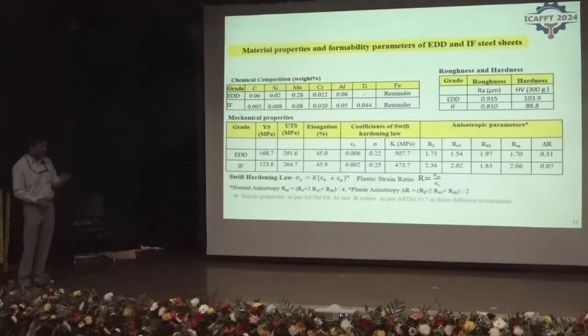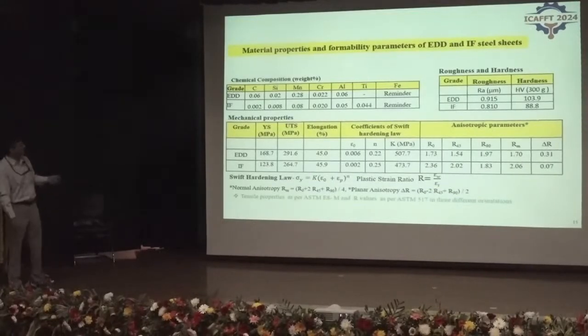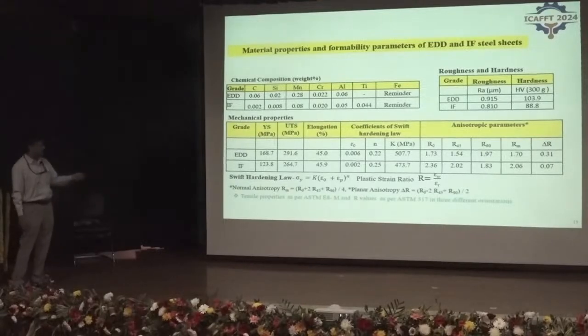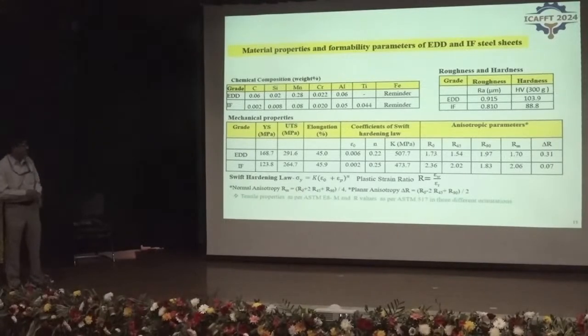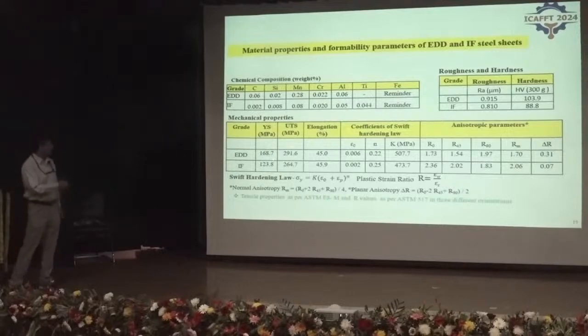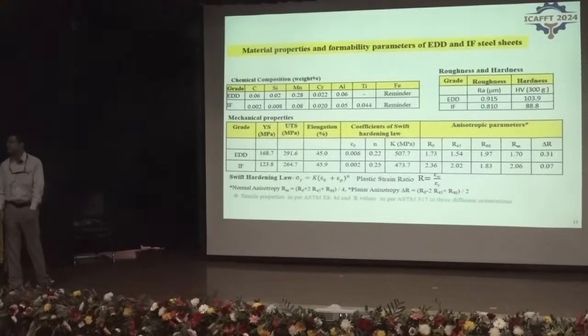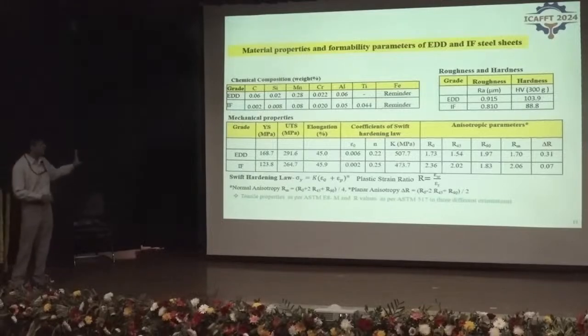So you can see here the comparison of material properties, the general mechanical properties and formability parameters of these two: extra deep drawing steel, and the second one is IF steel, which is interstitial free steel. Even though the strength of IF steel is slightly lower than the EDD steel, the strain hardening exponent and the anisotropic parameters are higher, indicating its better stretchability and drawability, so that the overall formability of IF steel is definitely better than that of EDD steel.